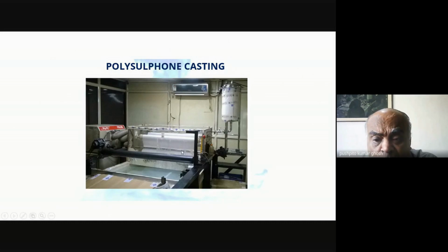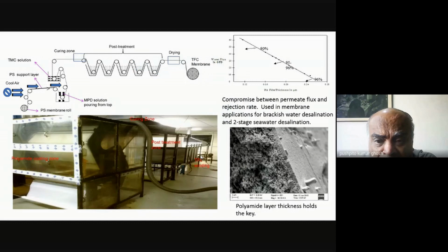So for example, after a lot of painstaking effort, it was found that the refractive index changes which take place in the water because of the presence of small amounts of solvents like DMF can actually be measured to the 4th decimal place through special instruments. So that can be used as an online technique to tell you whether you're doing things right. So I hope you can understand the sensitivity.